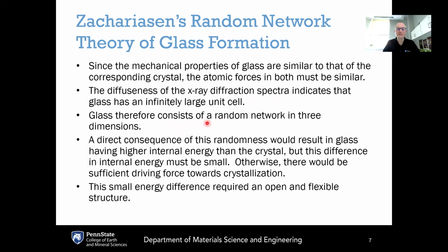Therefore, glass consists of a random network in 3 dimensions. It has to be in 3 dimensions because he has a 3-dimensional piece of glass, and because it has an infinitely large unit cell, that means that the glass network must lack repeat units, which means that it has to be a random network. A direct consequence of this randomness would result in glass having higher internal energy than the crystal. So let's stop there for a moment.